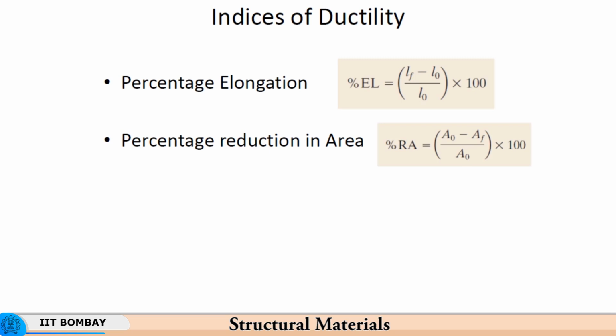Immediately after that, let us say necking takes place, then the reduction in area takes place further, and then let us say like gold, supposing the material were to fail at a point, then the reduction in area would be the sum total of the reduction in area in uniform deformation plus reduction in area during plastic deformation, and you will get practically the entire area. So, 100% would be the reduction in area for materials like gold, because A naught by AF is practically 0, and therefore, you will have a very high percentage of reduction of area.